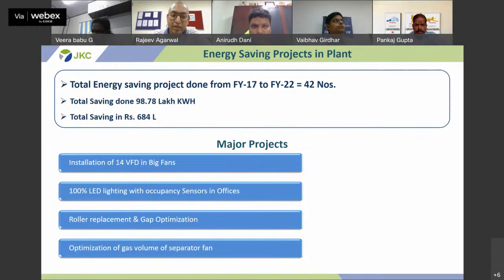Then, sir, roller replacement and gap optimization. Last year we replaced our roller, and we regularly optimize our roller gap to maintain the grinding of clinker and for better power optimization in the roller press. Sir, then in 2019, we optimized the gas volume of the separator fan and arrested the false air in the separator fan. It gives us lots of benefits and helps us reduce the power of the separator fan.